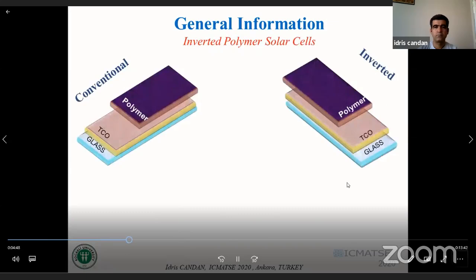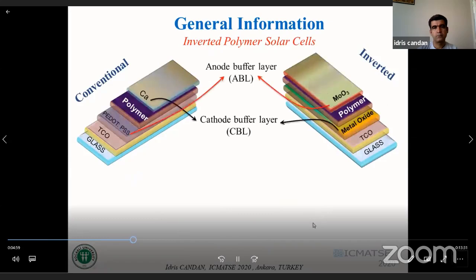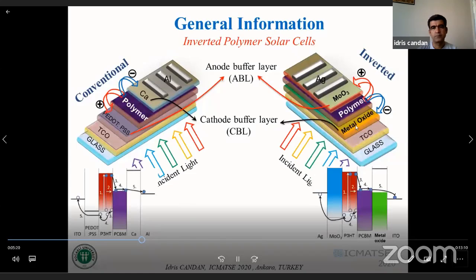When we look at the differences between conventional and inverted solar cell structures, the main difference is the change in the position of the anode and cathode buffer layers, as you see here. The calcium layer is replaced with a metal oxide and PEDOT:PSS is replaced with molybdenum trioxide. And the position changed. Electrons are collected in the metal oxide in the inverted polymer solar cell, but in the conventional solar cell, electrons are collected on the calcium side. And light in both structures comes from the glass side.